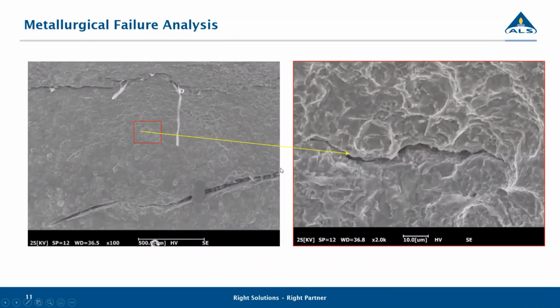If you look a little bit closer to the surface just above the weld, there was also a lot of secondary cracks. So the cracking actually didn't start from the weld itself or from the bracket, but it was just above that location. And you can see here, that's the little red section. If you zoom in there, you can see these secondary cracks that developed there, quite sharp ends, and that was on both sides of the brackets. A lot of secondary cracks developed in that area as well.